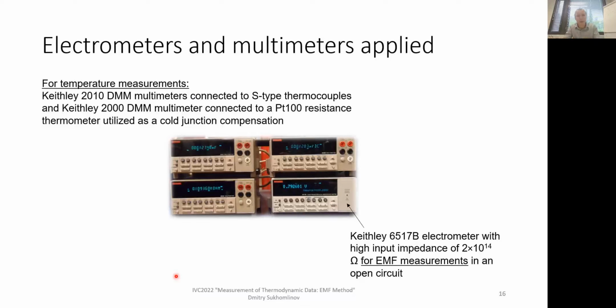A bit more about these devices. So we had a rather sophisticated approach to measure temperature. One device had been measuring room temperature with a PT100 resistance thermometer, and then 2 others had been measuring temperature difference between hot junction of the thermocouple and cold junction. And these 2 thermocouples were inserted from 2 different sides of the galvanic cell to minimize temperature gradients. And here we have the number needed for input impedance to make sure that measurements are really done in open circuit.